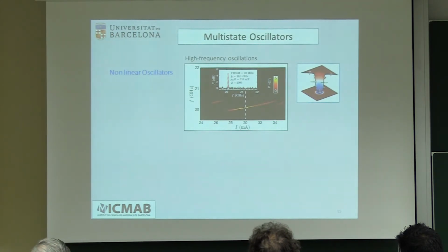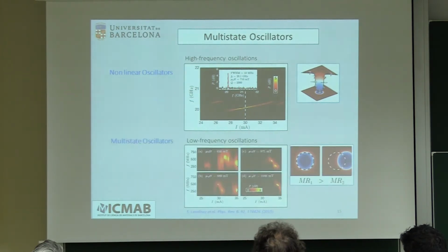What else? Those devices, different from a normal spin torque oscillator, are very localized and depend on the effective field. And in a film that has different grain sizes and different anisotropies, what happens is that you have an effective field landscape. When you have that, what we see is that you have different oscillations. So you have different states of oscillating.